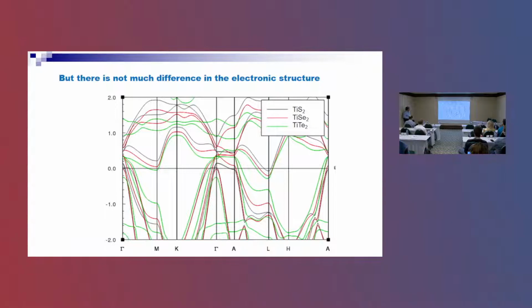If you look at a simple picture, band structure calculation, GGA, we see that there is no big difference between all these materials, titanium disulfide, titanium diselenide, titanium ditelluride, from the electronic band structure point of view. In all these cases, we have hole-like pockets around the gamma point and electron-like pockets around the L point. So basically, in all these materials, we have so-called nesting, when we have similar in volume hole-like and electron-like pockets, which are shifted by some vector q.